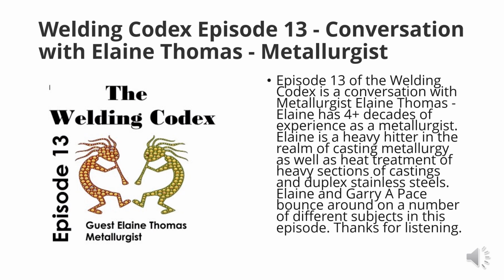But it gets back to, like you say, locking that matrix in place where you want it and without that sigma phase. Correct. Once you get rid of that sigma phase, you can start to work with the casting, because now it has ductility, it has strength. You can start putting a torch to it to carve off risers or whatever superfluous pieces are on it, and to work with the casting.